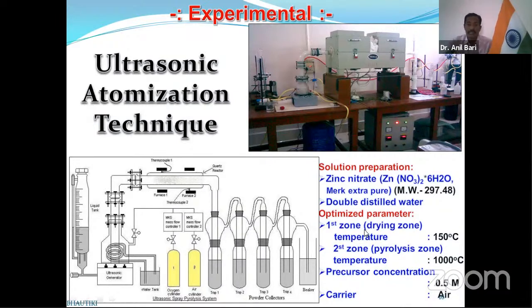Now, an appropriate molarity of zinc nitrate solution is poured into this liquid tank. This liquid tank slowly delivers the solution into the ultrasonic atomizer. This atomizer consists of a piezoelectric transducer. This transducer converts the solution into a fine mist. This mist is pushed forward with the help of this oxygen or air cylinder, and it is put into the first zone temperature, or the first furnace. The temperature of the first zone is 150 degrees centigrade. It removes the water from the mist. Only the dry particles remain. Then these particles are pushed forward to the second zone temperature.